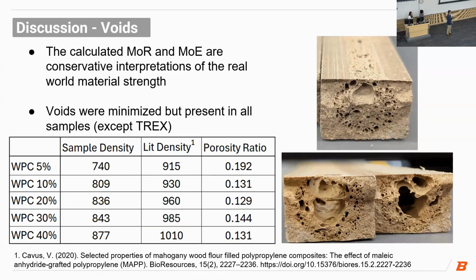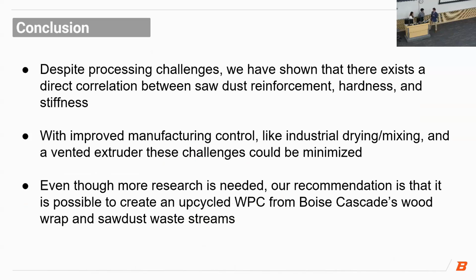Throughout this process, we were able to improve the extrusion techniques that we were utilizing and refine our processing to eliminate voids as the project progressed, but we were unable to do so completely. This, however, doesn't impact the final conclusion of our project, which was determined using trends and comparison between different samples rather than any individual numbers, which have that unknown error in their accuracy. And so to provide that conclusion, here is Joselyn.